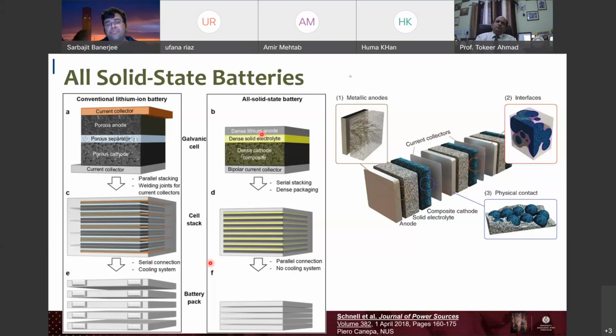So a real major push that is going on is to build all solid state batteries with lithium metal anodes and dense solid electrolytes, where you can somehow mitigate lithium dendrite formation, and then to have a dense cathode composite. So very high capacity on the anode side, high capacity on the cathode side, and then a fully solid electrolyte that somehow prevents the lithium from coming through. And they would again be connected here. And if you got it to work in the right manner, you wouldn't even need a cooling system. So here's a graphic that I borrowed from Dr. Piero Canepa.